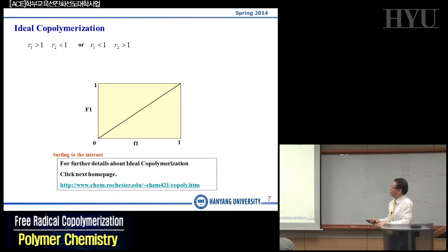When we have ideal copolymers, usually the small f1 monomer mole fraction could be plotted against the monomer mole fraction in the copolymer, just like a distillation curve in your chemical engineering case. And you can form an azeotropic line here, where small f1 is equal to large F1. You can plot it with the same lines here, and this is what we call the ideal cases.